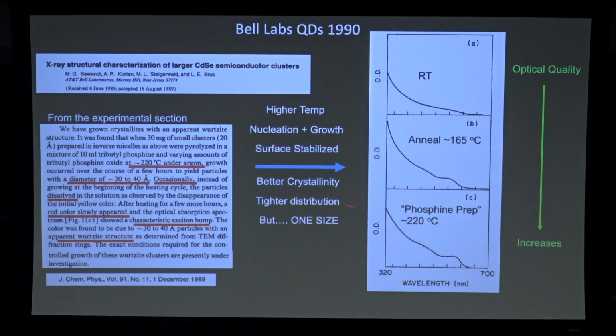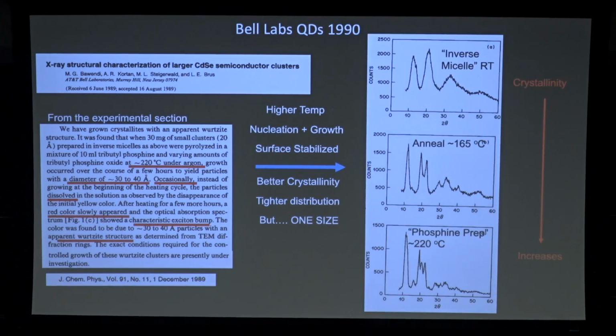Better crystallinity, tighter distribution. The crystallinity here, this is a powder X-ray. The width of these peaks is inversely proportional to the crystallinity. So as they get narrower, that means better crystallinity. These 3 peaks mean that this is really the bulk that you're looking at here. So this is all great. But I could only make one size every now and then.